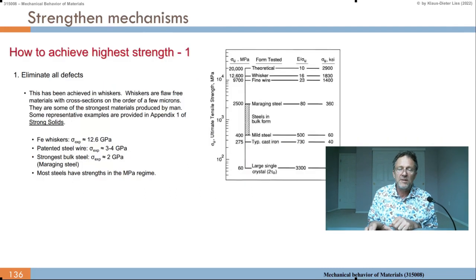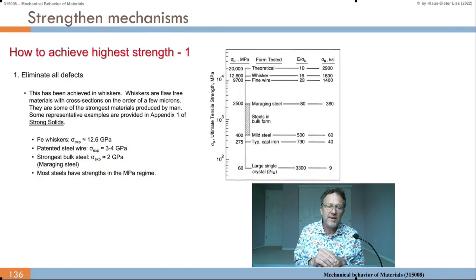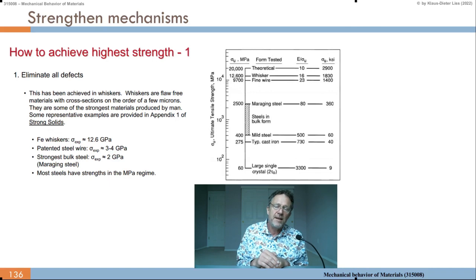Today I would like to emphasize the dislocations. So how to achieve the highest strength? First of all, we can eliminate all defects, because if there's no defect in the material, like in a whisker, in a single crystal, then we first have to nucleate a dislocation. And that nucleation needs to overcome some energy barrier. Crystals without defects and of very high strength have been achieved in whiskers. Whiskers are flaw-free materials with cross-sections of the order of a few microns, and they are some of the strongest materials produced by man. Some representative examples are provided in Appendix 1 of this publication, Strong Solids.